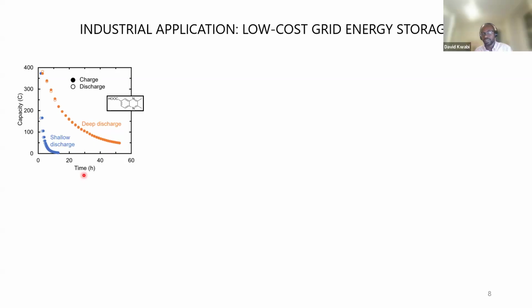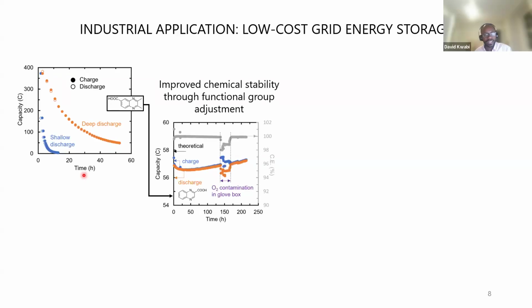By applying the same spectroscopic techniques that I just introduced, understanding the mechanism of degradation, we're able to select a slightly chemically modified version of this molecule with a carboxylic acid in a different position. So you can see here, the carboxylic acid on this molecule is in the 6th position. Here it's in the 2 position. And we're getting rid of the 2 methyl groups that used to be here.